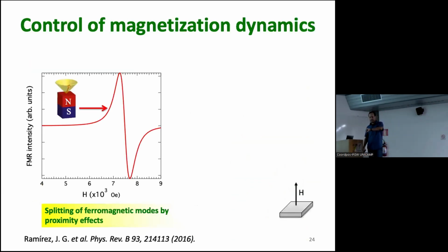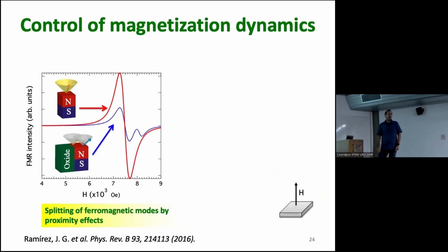So the results are the following. By looking at this geometry, this is the sample, and then I apply a perpendicular magnetic field. So I get something like this. At high temperature, I get just one single resonance. Okay. In between, just in the transition, I get something like this. There are two resonances. And then again, the question will be why there are two resonances. And this is only happening in the oxide. This is the nickel only, and this is the nickel with the oxide.